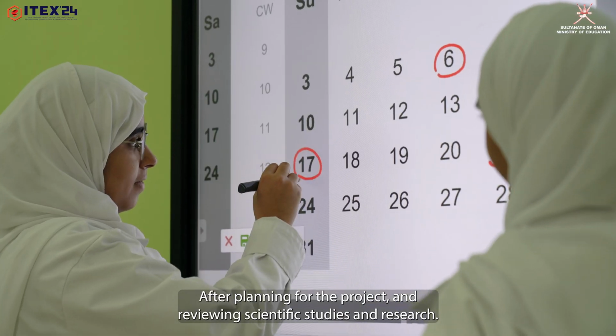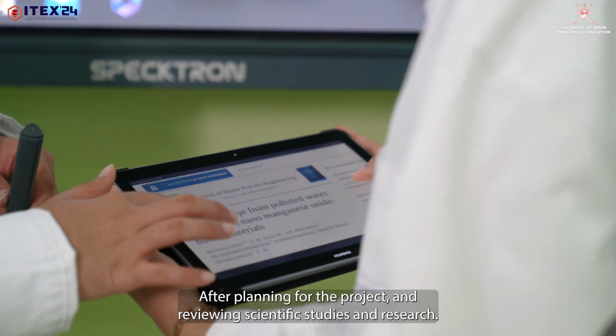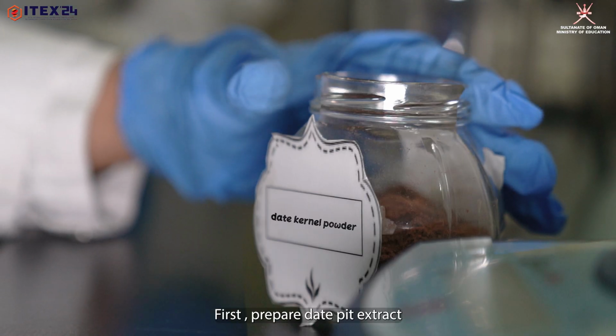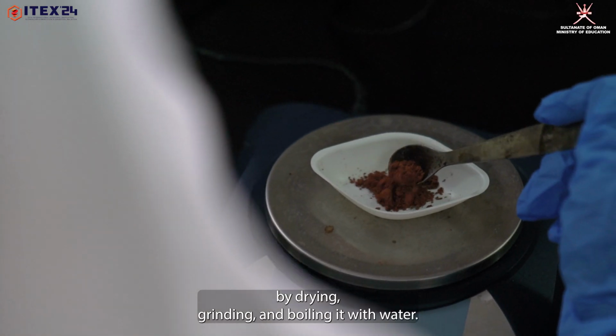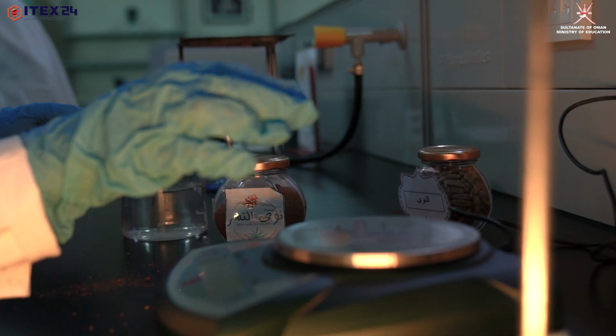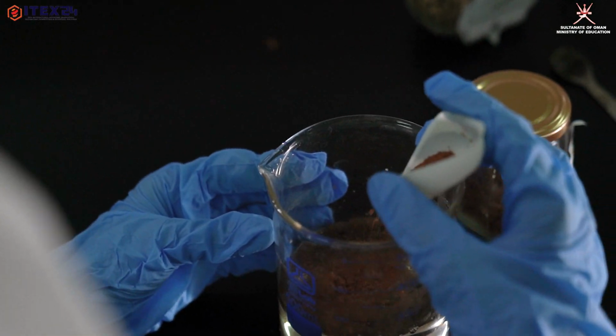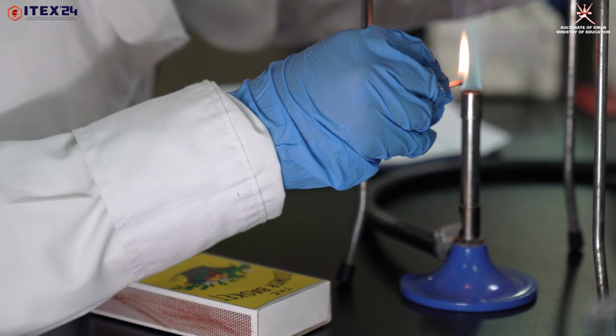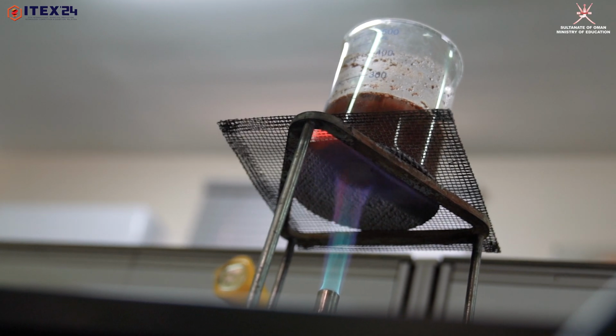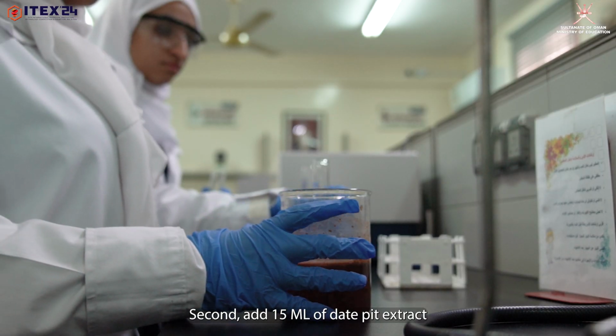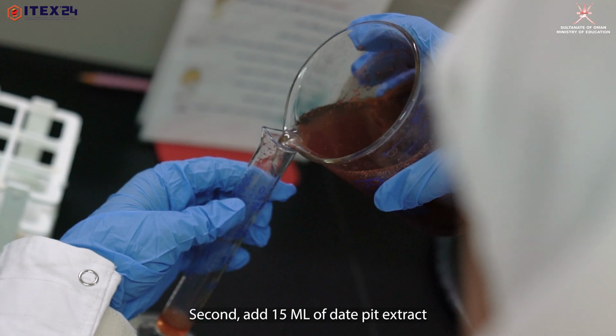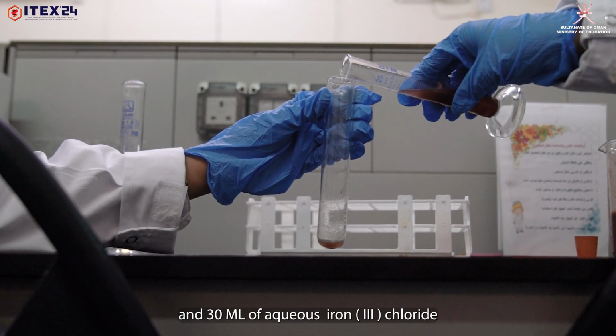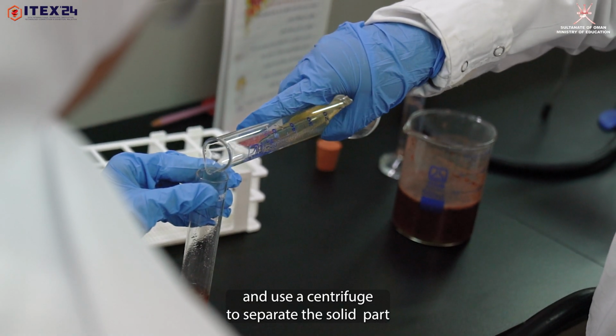After planning for the project and reviewing scientific studies and research, the experiment was implemented. First, prepare date pit extract by drying, grinding, and boiling it with water. Second, add 15 ml of date pit extract and 30 ml of aqueous iron(III) chloride and use a centrifuge